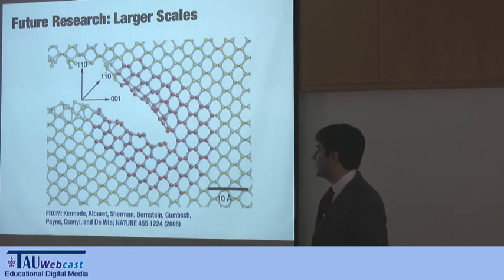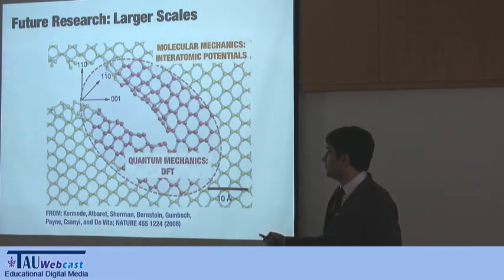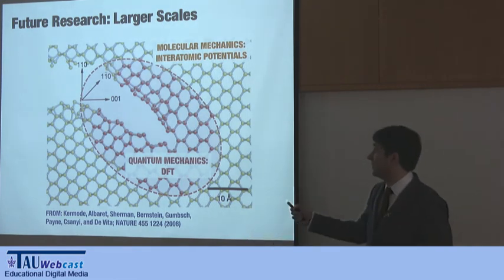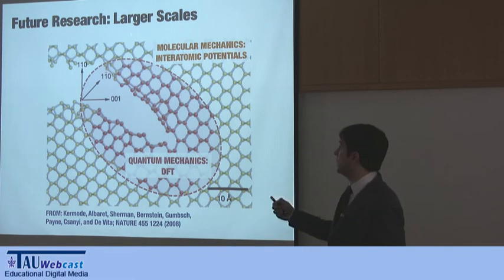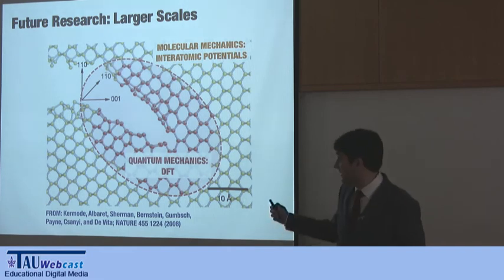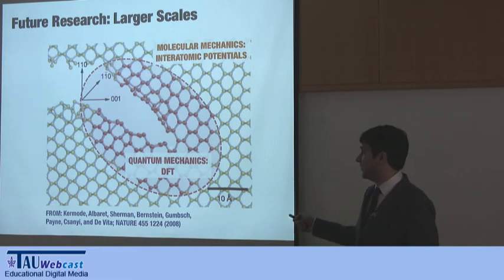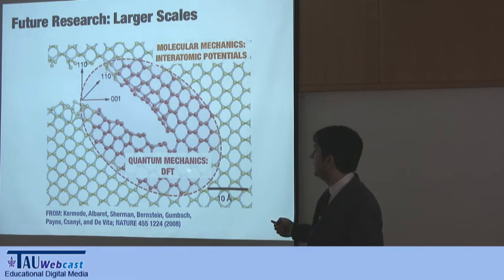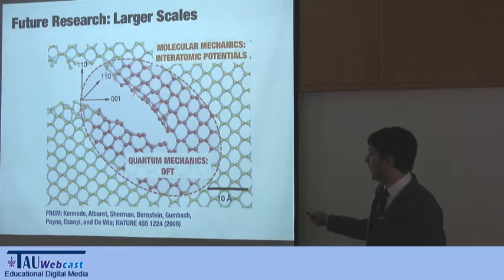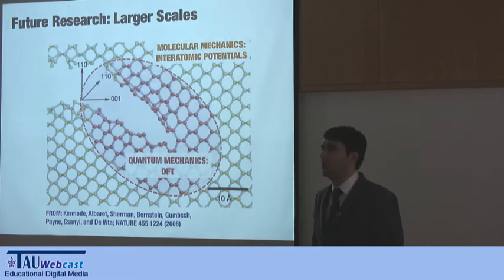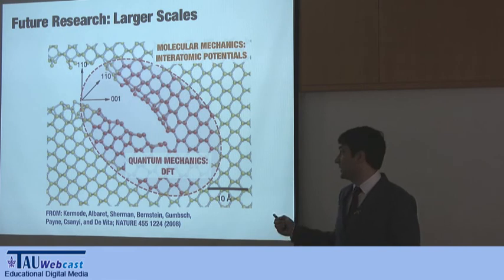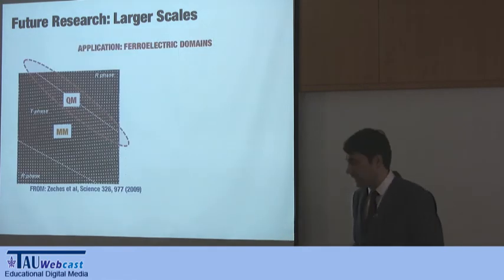So what they use is what is called a QM/MM method, in which you treat the quantum mechanical part with DFT, and you treat the rest of your material with something cheaper, like those potentials I told you about. So in this case, the crack is moving. You are doing the simulation quantum mechanically where the tip is, and every time the crack opens, you move the area in which you do the simulation, and you have to get these two parts together, but there are ways to do it. So you are basically getting DFT accuracy for a system that otherwise you couldn't treat.